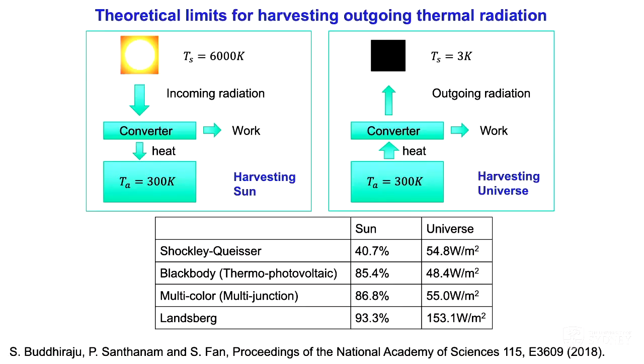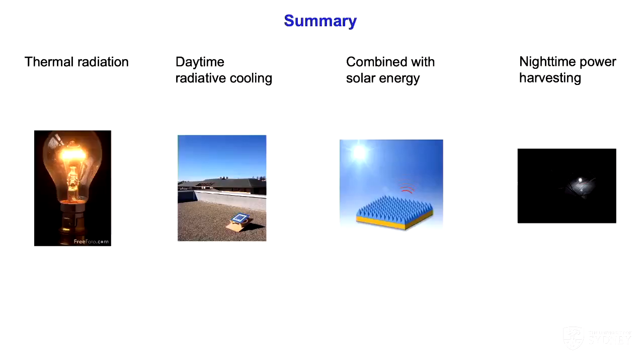And those numbers range from about 50 watt per meter square to 150 watt per meter square, depending on the scheme. Now, the experiment that I showed you has a power density that's about 2 to 3 orders of magnitude below this. And as a theorist, I would say that that represents a great opportunity. It means that there's still a lot that one can do to further improve the material and the device to push this idea of harvesting outgoing radiation forward.